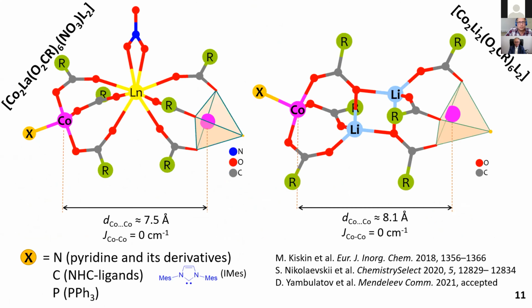In this presentation, I will talk about the problem of sign switching of the zero field splitting parameter in carboxylate complexes, since the majority of such complexes are characterized by positive D value. I will start with tetrahedral complexes. This slide shows two types of cobalt complexes in which each paramagnetic atom is surrounded by three oxygen atoms of three carboxylate groups and one donor atom of a neutral ligand, like this one and this one. These complexes are polynuclear, and cobalt atoms are separated by lanthanide atoms or two lithium atoms.